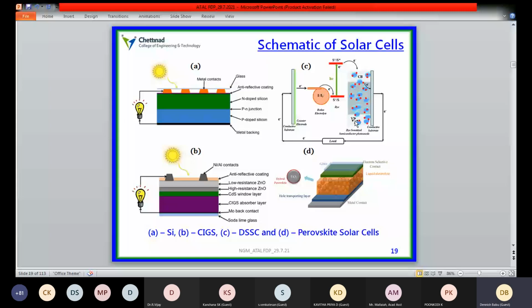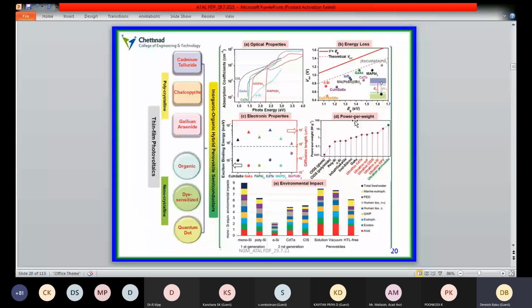So this is the classification of the various thin film based materials so far utilized for photovoltaic purposes. Compared to the traditional cadmium telluride and gallium arsenide based systems, methyl ammonium bromide and methyl ammonium iodide, which are called hybrid perovskite materials, have an absorption coefficient in the range of 10 power 5 to 6. It is predicted that they can be used for industrial level fabrication of solar cell devices for future photovoltaic applications. It is also predicted that this material has a lower environmental impact than the traditional materials: silicon, amorphous silicon, cadmium telluride, and copper indium sulfide based materials.